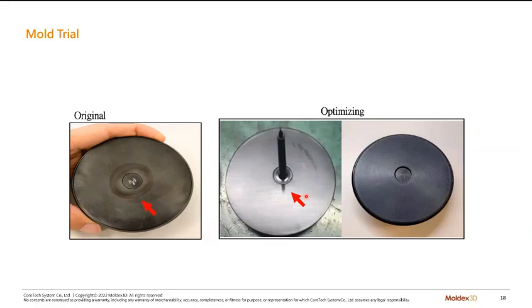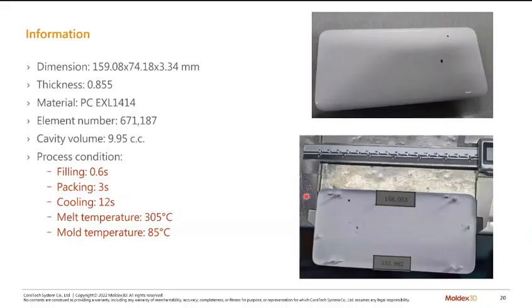Okay, this is the first case. And the second one is the uneven shrinkage issue. This part is sort of a cover, and at the very beginning, they found that the dimensions on the top and bottom have a difference that is not acceptable to the criteria. Right now it is 0.15 millimeters. And here is the basic information of this part. The material is PC, and the thickness is quite small, around 0.85 millimeters. And here you can see the basic process conditions.